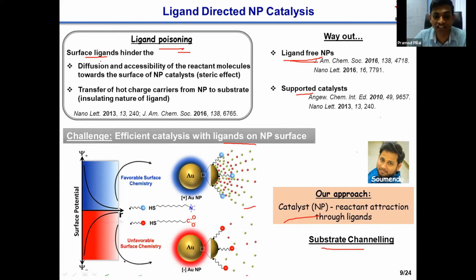In this case, we have selected electrostatic interaction. And the reason for the electrostatic interaction is as follows. Most of the reactions that we are interested in are in water. So in water, most of the molecules will be charged. So if you can control the surface potential around a nanoparticle, you can control this catalyst-substrate interaction.